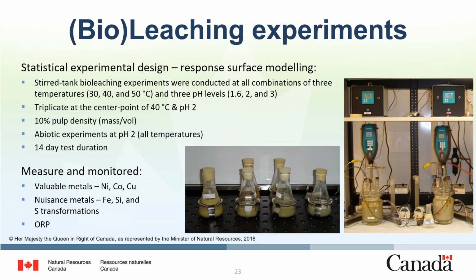We conducted a number of stir tank bioleaching experiments at various pH and used surface response modeling and analysis of variance significant testing to assess the effect of temperature and pH. We tracked the concentration of the primary metal values, nickel, cobalt, and copper, as well as the primary nuisance metals, in this case iron and silica.